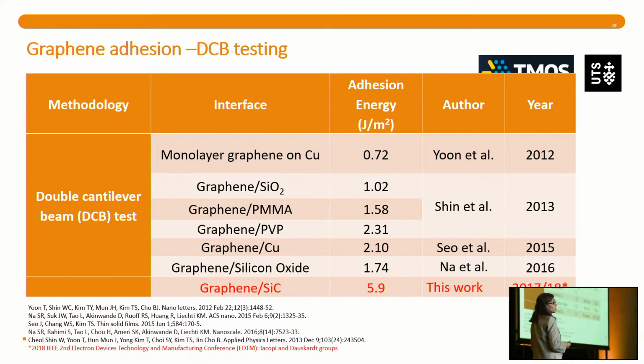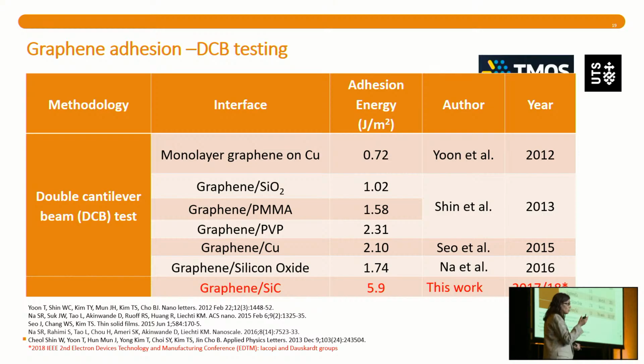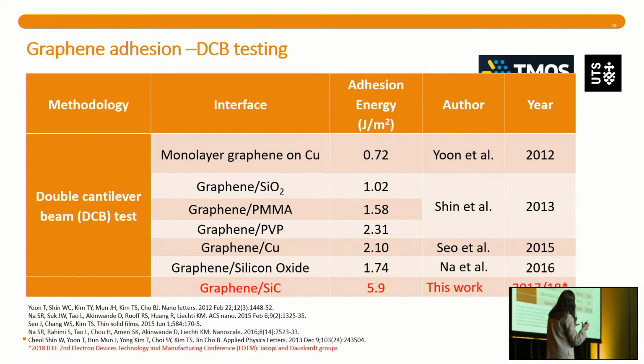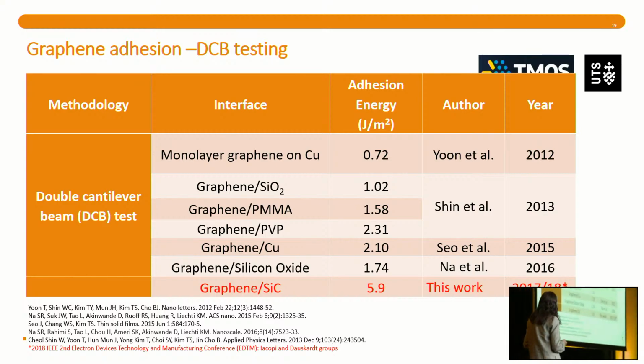Now, it turns out, remember that this graphene that I'm talking to you about has a smaller grain size, about 100 nanometers, judging by the 0.2 figure. And we measured the adhesion on our samples, and it's almost 3 times as high. So basically, our model is that around the boundaries of the grains, we do have some bonding. The grains are clean, but around those 100 nanometer boundaries, we do have some bonding with the substrate. Which is basically a sweet spot, because we can work in integration with 6 joules per meter square.